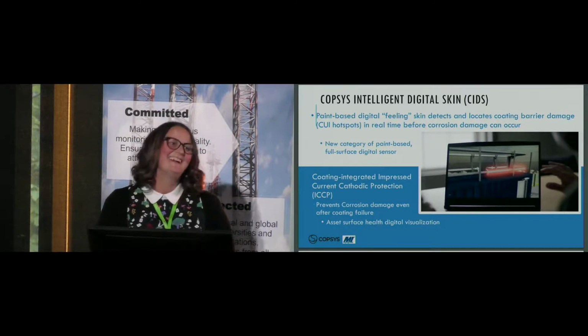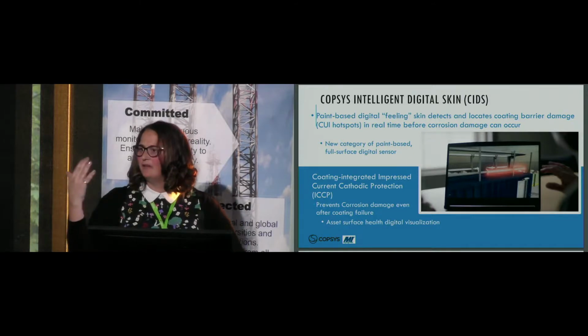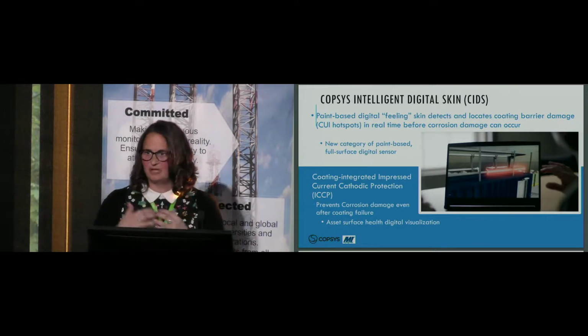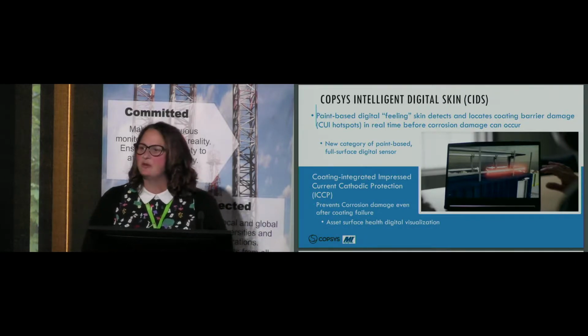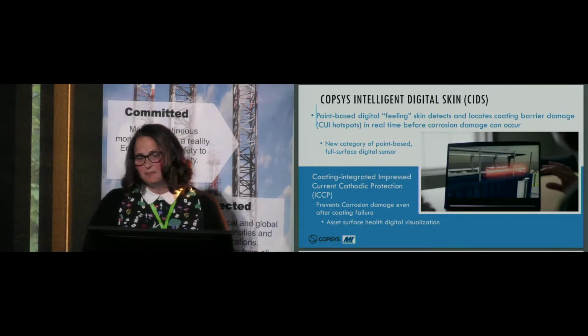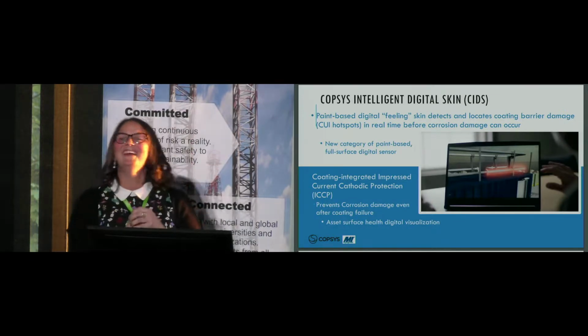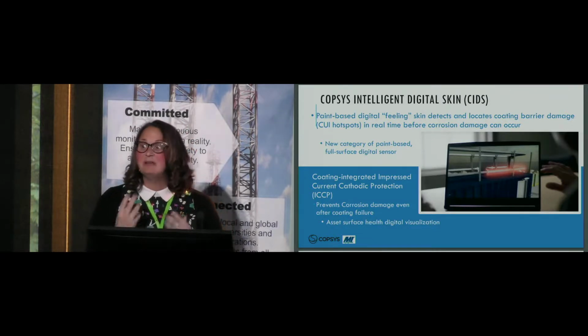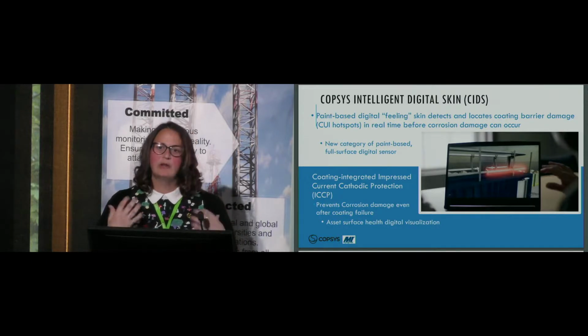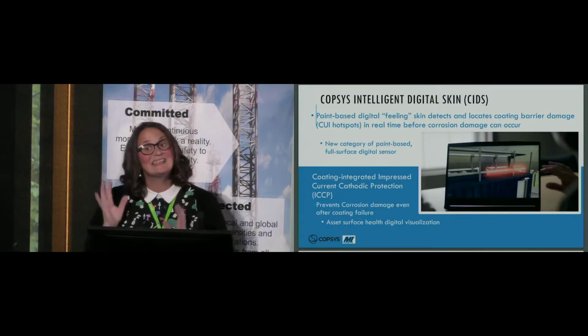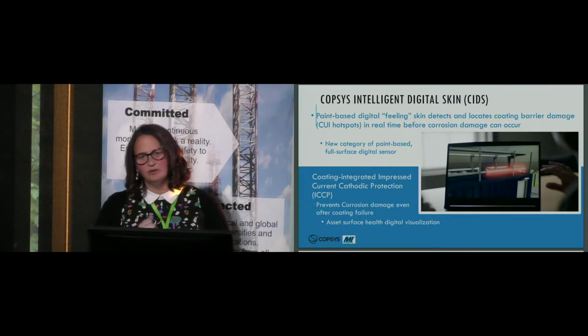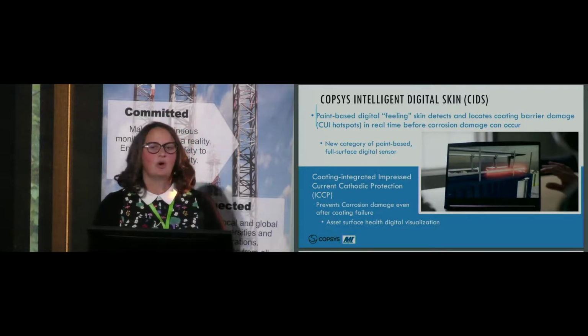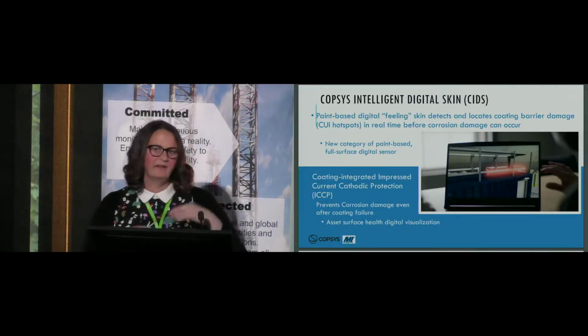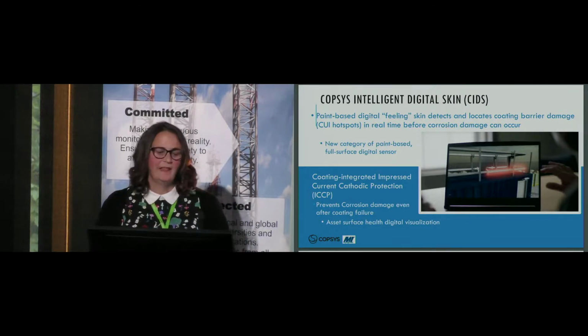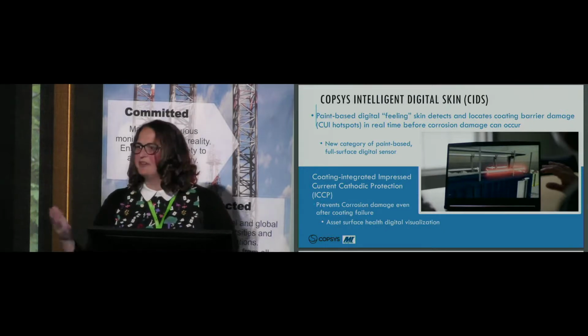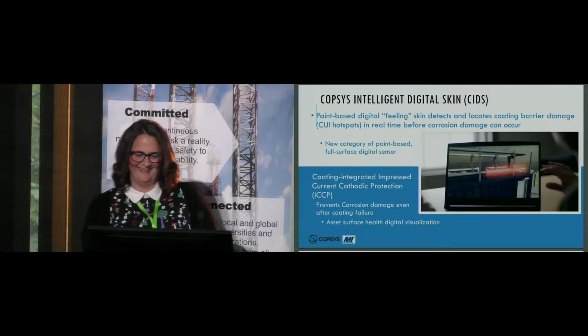But on top of that, luckily, even if there is coating damage, you have long turnarounds for big maintenance planning. So you have dry dock in a year. With this, because, as Tony so nicely talked about, ICCP, Impressed Current Cathodic Protection, is built into the coating. The coating itself provides the system, the CIDS system provides really low voltage ICCP. So even if there is damage, and even if the electrolyte's there and the connection is there, it's not going to corrode. And that is the beauty of this. It seems wrong based on everything we've said. It seems like, well, that can't be true, which is where I started.